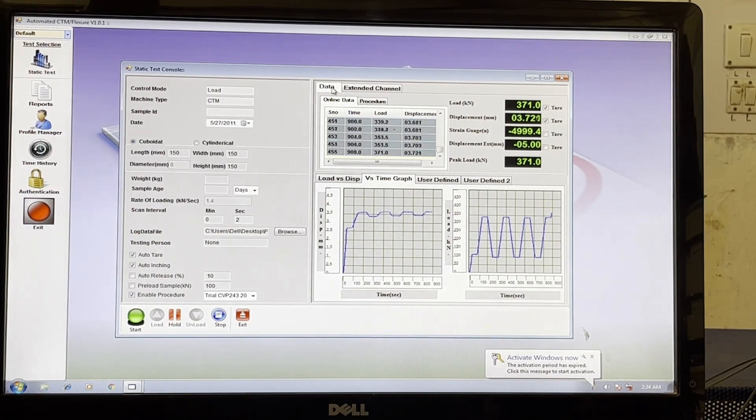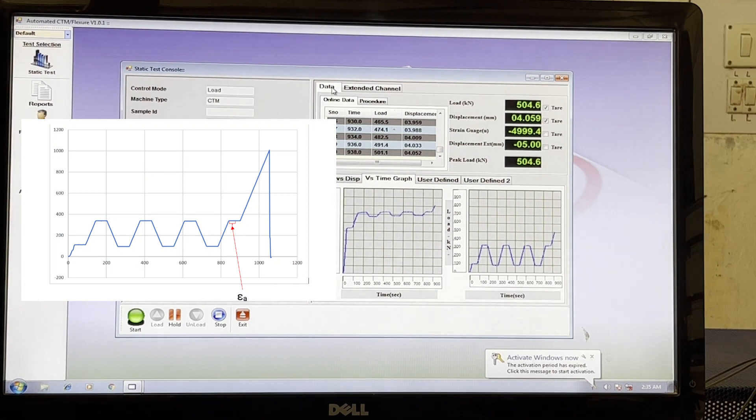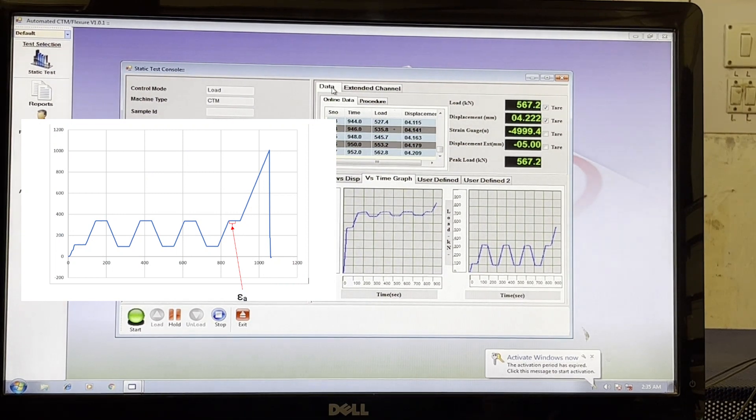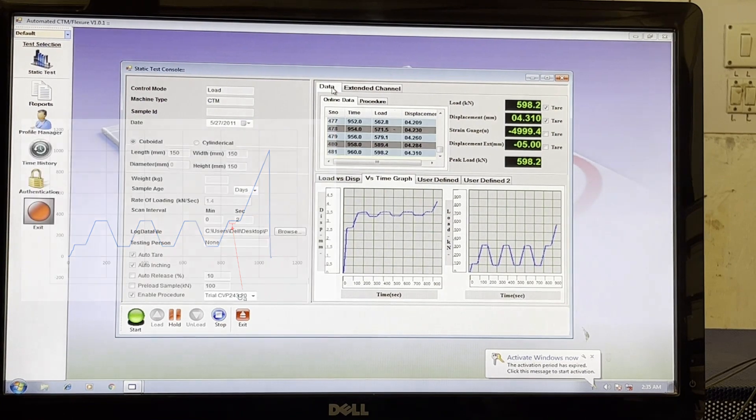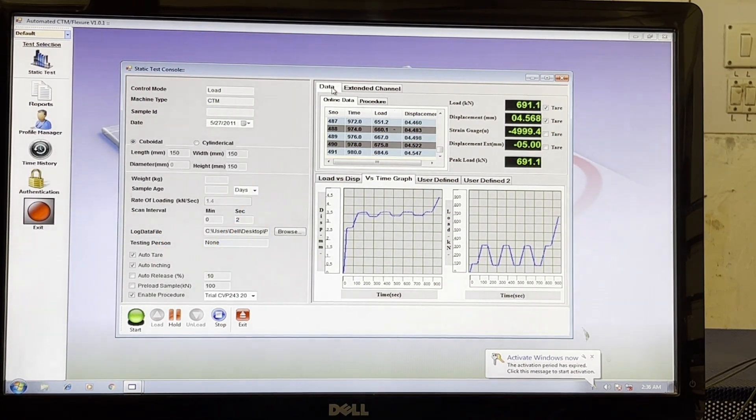Increase the stress at the constant rate until the stress equals FC by 3, maintain for 60 seconds. During the succeeding 30 seconds, measure and record the strain readings taken at each measurement line epsilon A.